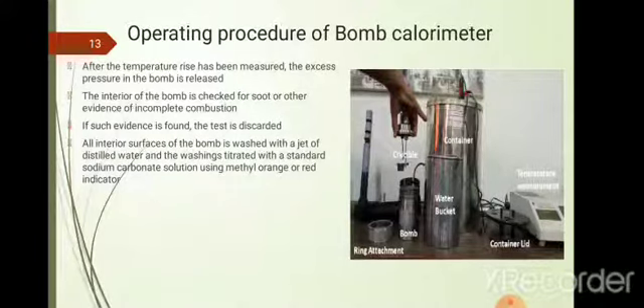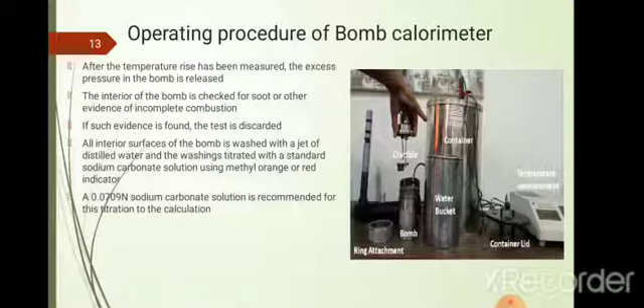After the experiment, the interior surface of the bomb is washed with a jet of distilled water. This distilled water, after washing, is titrated with the standard sodium carbonate solution, using methyl orange or red indicator. Normally, 0.0709 concentration of sodium carbonate solution is used for titration.